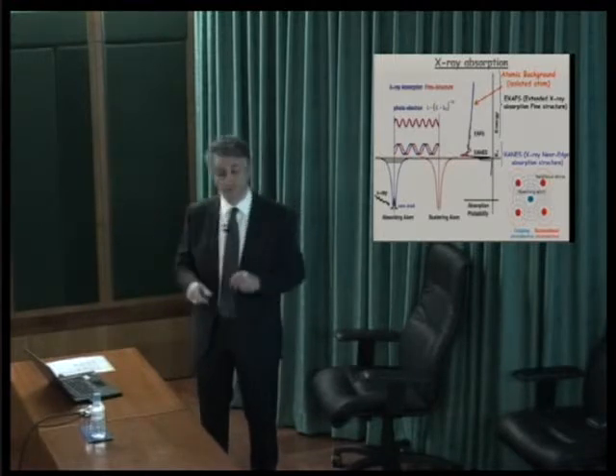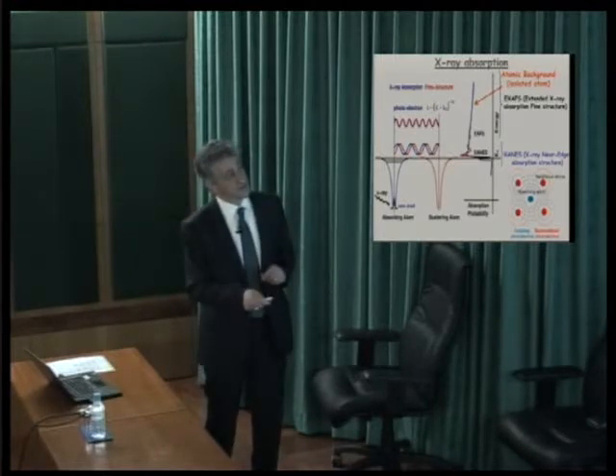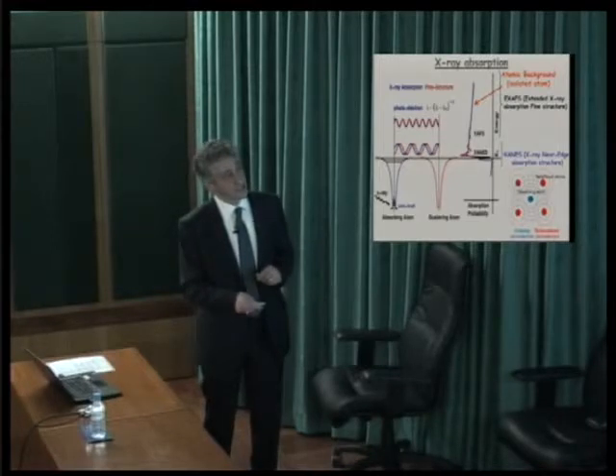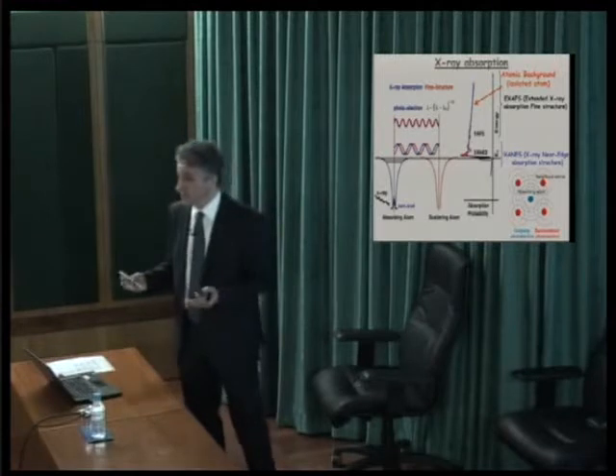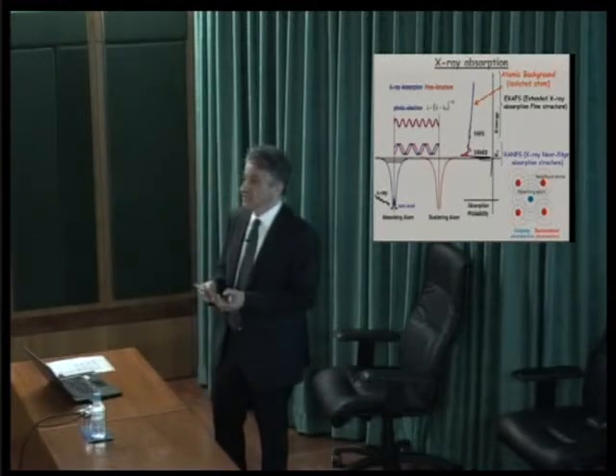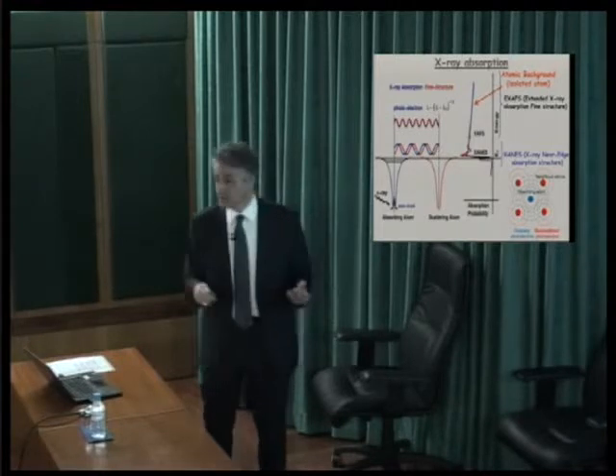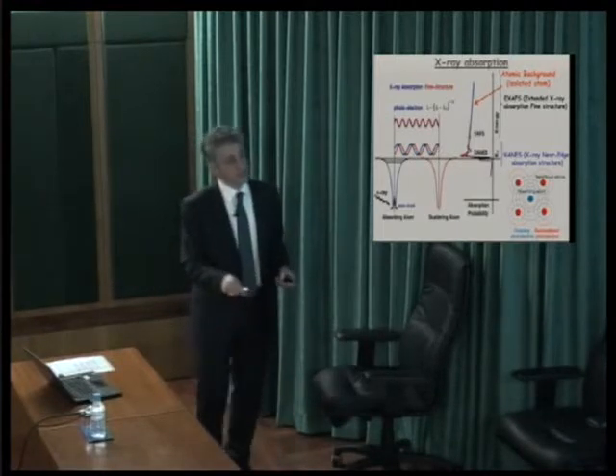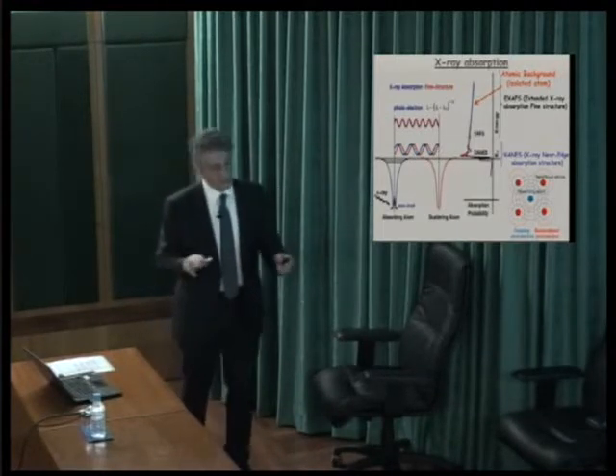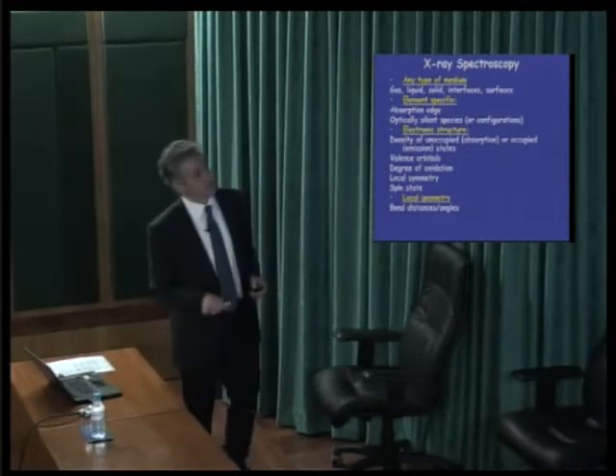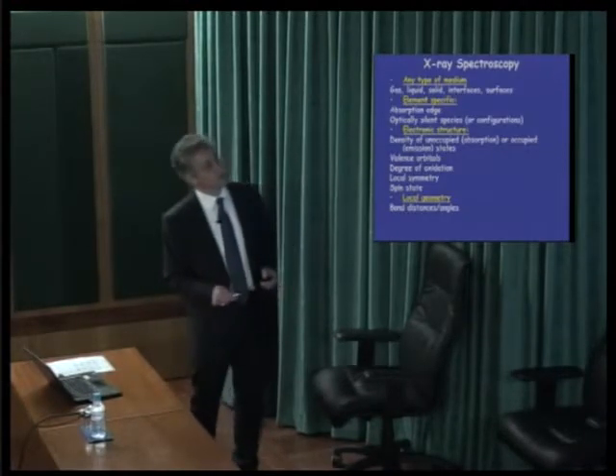In a nutshell, you subtract this atomic background, you end up with a spectrum in energy, which you convert into wave vector, they're proportional, and the Fourier transform of wave vector is angstroms, and therefore you get the local topology around the atom. Okay, this is really very crudely said. So these are the reasons why we went to X-ray spectroscopy.